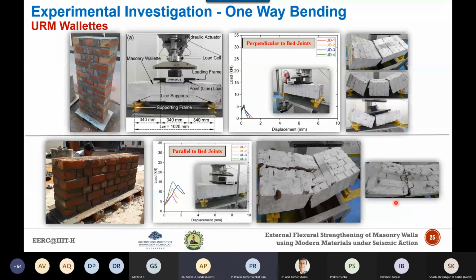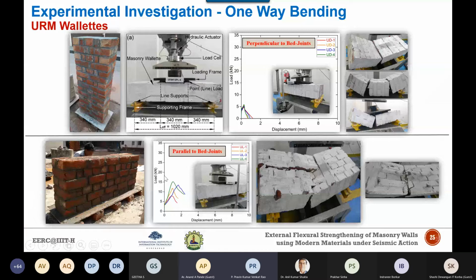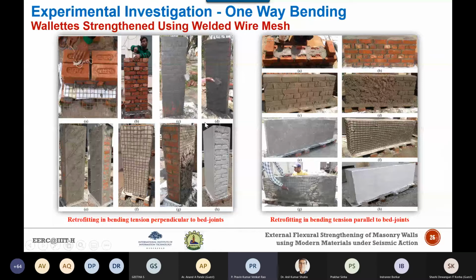Now, what we did is we tested the same unreinforced masonry by retrofitting or strengthening using wire mesh. Here you can see that in between the different courses of the brick, we have applied our dowel bars. What we did is we applied a first layer of the mortar, then we applied this welded wire mesh as a layer, and then in order to join the masonry substrate and this wire mesh together, we have used these dowel bars. These dowel bars have been laid while constructing these masonry specimens, and once the mesh has been applied, these have been bent so that integral action takes place.